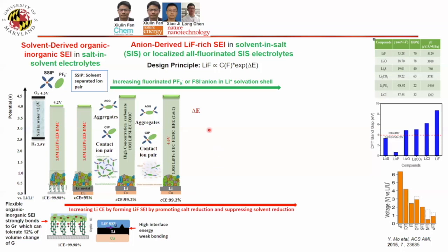And then we think the second method is to increase the gap. We add ether, because ether has a much lower reduction potential, like THF. THF is reduced at 0.2, 0.3 volts, but PF6 at 1.2, 1 volt. So they have a huge gap here, and in this case we have a high chance to reduce the PF6.